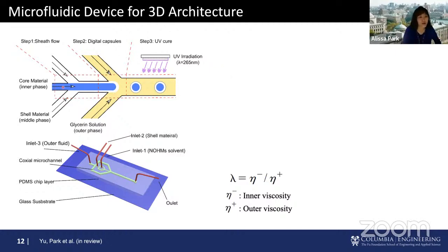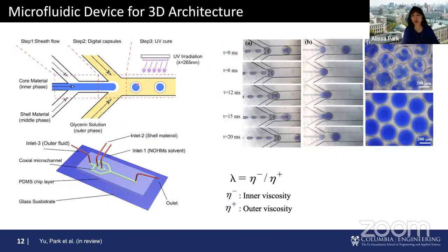So if you look here, this blue fluid is just blue, with the blue dye, we put NOHMs inside, and this white fluid is UV curable polymer. So you create the droplet inside a droplet, and then in the second stage, you can UV cure, which cures only this UV cure polymer, which is in the outside layer as gas permeable layer. And here are some of the examples of what we actually made.